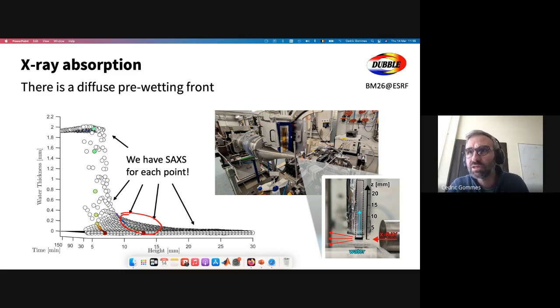So what is being done? You have this carbon here touching water, and water is climbing, and we're shining X-rays through them and measuring the scattering intensity as a function of time when this capillary rise happens. So that's the experimental part. And now you need the simulation, if you will, to convert these scattering data into structures. So for the data analysis, you rely on models, but it's models for data analysis. So it's not simulation from first principles of physics, if you will. It's simulation to solve an inverse problem and reconstruct the structure from scattering data. Does that answer your question?